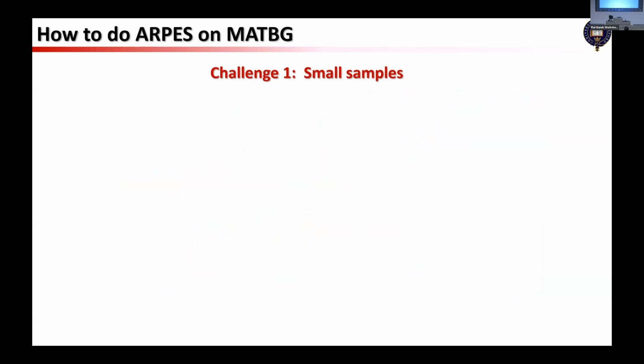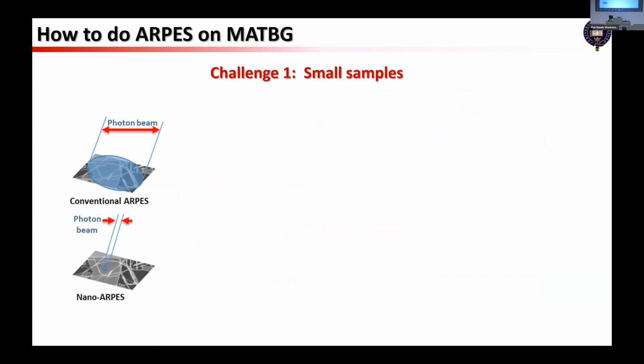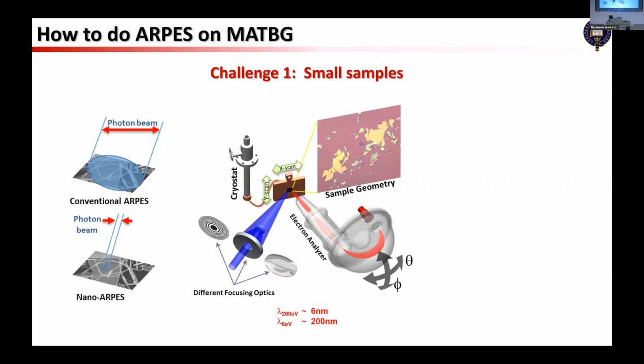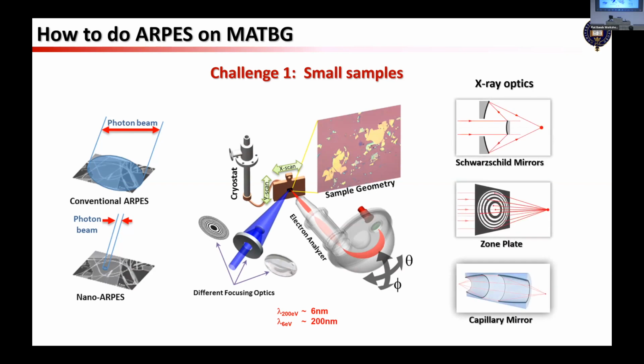The first challenge is that the samples are too small for the regular ARPES studies. You remember that typically our beam spot is about a few tens of microns to even a millimeter in size. So obviously what we measure is not the signal from the sample, rather it's from the substrate and other things. Until we can focus the beam spot down to a size smaller than the device, we cannot do it. Which finally happened in the past few years, and we were able to focus the X-ray beam from the synchrotron radiation source down to sub-micrometer. We dub it nano-ARPES, though in fact, micro-ARPES is more appropriate. We can focus the beam using different methods: mirrors, zone plates, or capillary mirrors. I will not go into the details, but with this technique, we can then scan the sample and find the interesting regime we want to study.